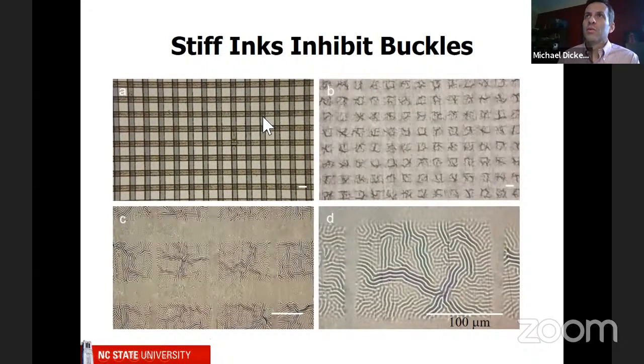So this is what the surface looks like before we shine the light. And then this is what it looks like after we shine the light and remove the ink. And you can see if you zoom in that the wrinkles are only forming in these little squares, and they're not forming in the space between them. So it was kind of interesting.